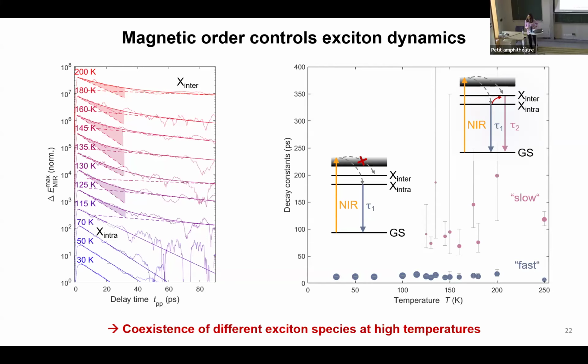Can I ask an experimental question? Yeah. On the left, there are quite a few fluctuations, which is presumably noise, or is there actual signal in there? Here you mean, on the left? It is noise. The signal was so small that we cannot conclude if it is something else. Because the measurement itself, you have this delay pulse, you change this, and I presume you do some averaging over some amount of time. So how long does a typical measurement last? Yeah, so above the Néel temperature, I think the full set of data took about 5-6 hours, and the more the temperature was growing, the more we had to accumulate. We accumulated a few cycles in order to get a better signal to noise ratio. And in the paramagnetic state, because of the finite dipole moment, we have a decreased response actually.